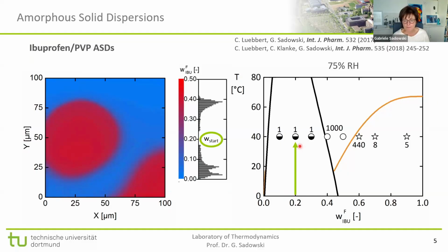And this was done for this sample, which was supposed to have a drug load of 20%. What you actually see is that no single point in the tablet has the desired drug load of 20%. Instead, we find droplets having a much higher drug load, and the continuous phase has a lot of polymer and a very small drug load. This is about 40%, and this is about 5% on average for the 2 phases, and this very nicely agrees with the points on the binodal, which is about 40% and 5%. So the prediction is not only qualitatively, but even quantitatively correct.